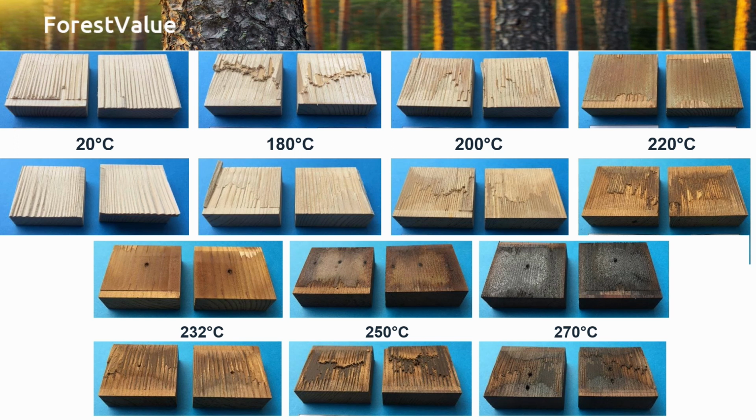So what you see is that, of course, the color changes drastically, and there's also the failure plane and the bond line is significantly different. For instance, when you look at the 270 degrees, in the case of the polyaddition adhesive, you see a kind of melting of the adhesive, whereas the lower one, which is an MUF, still shows a lot of fiber breakage.